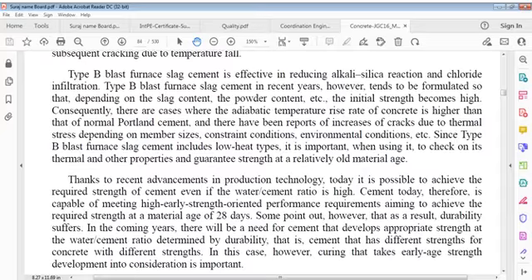Adiabatic temperature rise of all specimens with placing temperature 35 degrees was lower than that of a specimen with placing temperature 25 degrees, compared to tendency of maximum adiabatic temperature of concrete. Hydration reaction in early ages is activated as placing temperature of concrete increases, although temperature rise ratio in concrete increases, adiabatic temperature rise decreases. It can be explained by adverse effects of a high early temperature, which Verbeck and